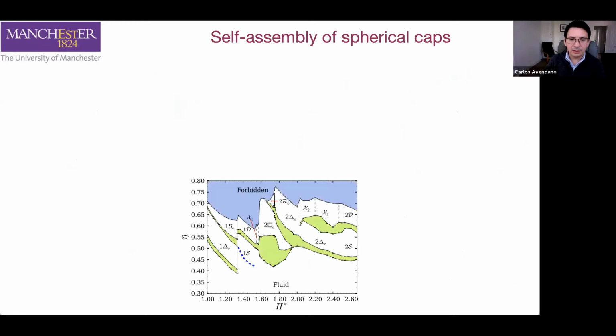And with that, we were able, using Monte Carlo simulations, to obtain the phase diagram for these particles. On the x-axis, I'm showing you H, which is the separation between the 2 walls in which the particles are confined. And on the y-axis, we have the packing fraction. So this is the volume occupied by the particles divided by the total accessible volume.